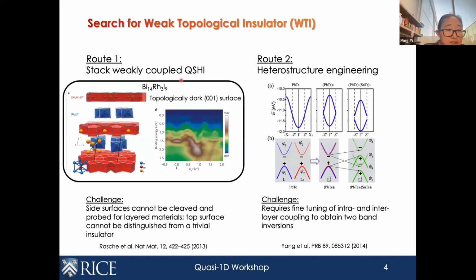So this is an example. There has been very nice work done in this field, but you can see this is one demonstration where we can only see the topological Dirac cone on the 001 surface. The other route is by heterostructural engineering, and here one runs into the issue that it requires fine-tuning of intra- and inter-layer coupling to obtain the two band inversions we need for the weak TI. And you can imagine that is also hard to realize experimentally.